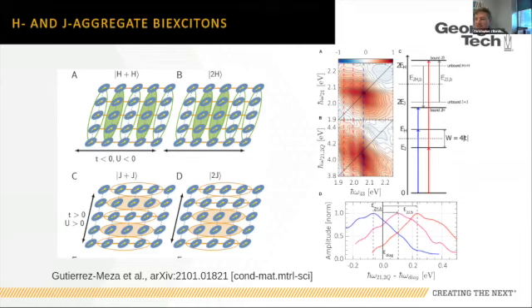Okay, so you anticipated the next question, which is, what are the intensities and what are the excitation densities that you're using for these experiments? Yes, so in terms of excitation densities, I should have run through it. The fluence is on the order of 30 nanojoules per centimeter squared, which is about a factor of 100 lower than typical pump-probe experiments in the low fluence range. I mean, not nowadays, but it's at least a factor of a few tens. So we were definitely in a low fluence regime. Like I said, we know that through analysis of this line shape, but also through our own population dependence measurements, exciton bimolecular annihilation is not a dominant pathway.